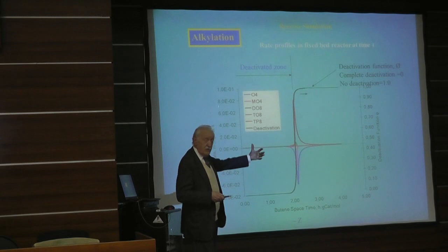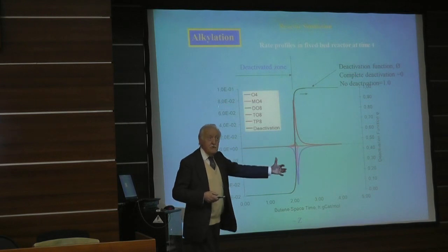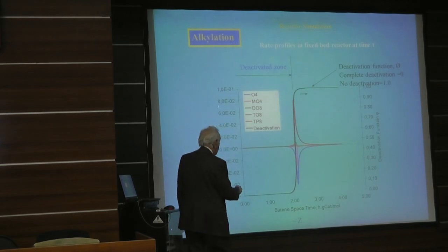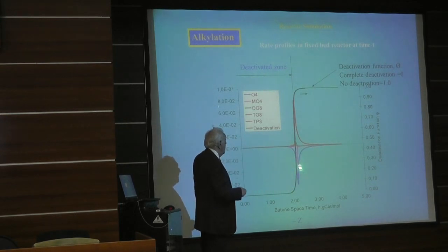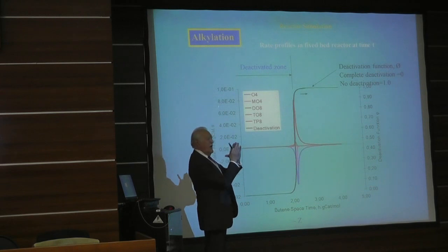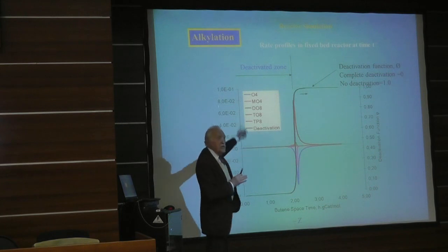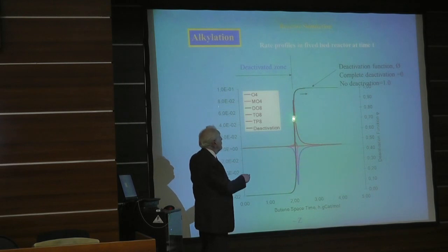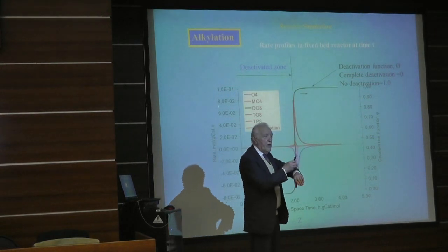Wait a minute. As we have seen with the propylene, after a certain while there is breakthrough of the intermediates indicating you have deactivation, and that is what you see here. So we look at it at a certain block time, and the reaction is extremely fast and is taking place in a very narrow zone because it is so fast. We've seen it with the propylene curve. And so everything takes place here where you have the products. But this is where the deactivation front has arrived after time t.